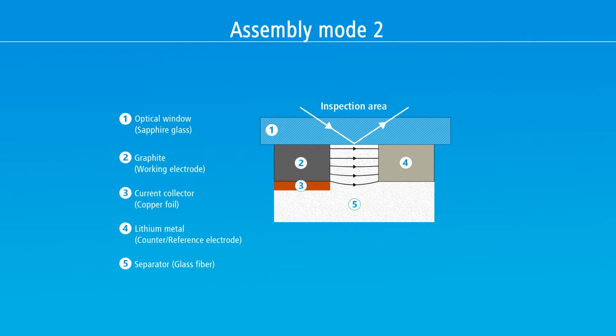the potentiostat. Importantly, the graphite electrode is placed with its active layer pointing towards the window on top. This way, the current cannot enter vertically through the copper foil, but only from the edges of the graphite strip. This side-by-side geometry results in a gradient of the local electrode potential along the width of the electrode strip, rather than along the depths of the graphite layer.